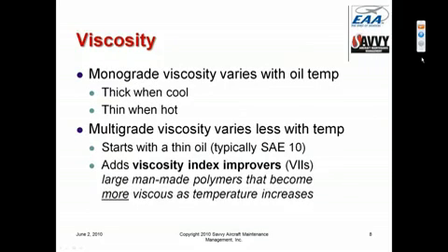Now let's talk a little bit about viscosity. Viscosity is the thickness of the oil, and monograde oils that are normally made of all petroleum oil, the viscosity varies considerably with oil temperature. They're relatively thin when the oil is hot at operating temperature. They get very thick when they cool to room temperature. And in fact, if it's real cold out, they get so thick that we can't develop oil pressure.